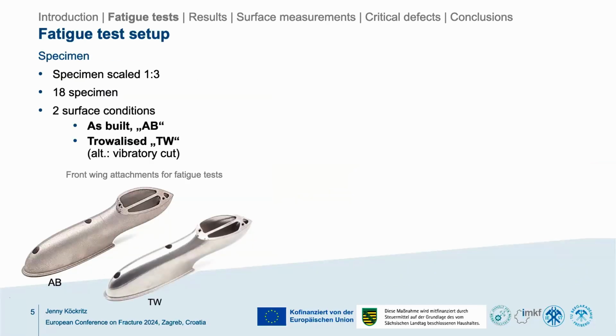To perform the fatigue experiments, the attachments that I showed you earlier were scaled at a factor of 1 to 3 to allow for more parts to be manufactured. And we tested 18 specimens in 2 surface conditions. Both types of parts underwent a T4 heat treatment before surface treatment, or no surface treatment, as is usual for this aluminum alloy. We tested as-built specimens, so only support structures removed, nothing else done, and trovalized, which some of you might know more under the term vibratory cut. And both of these are shown on the lower pictures here.